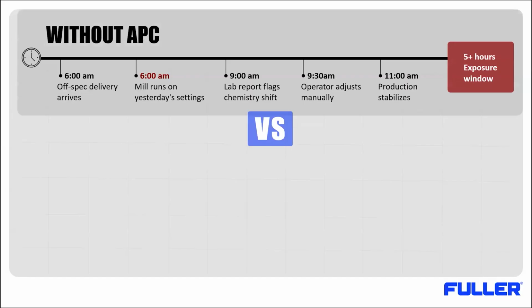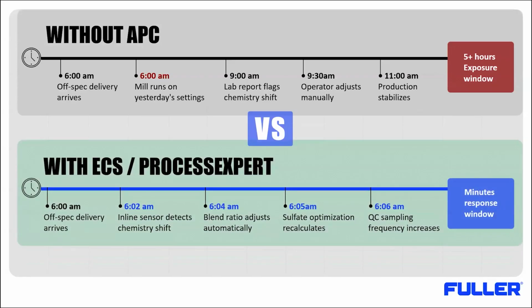The same Tuesday morning would look very different when the response loop is faster. Without advanced process control, the plant depends mainly on lab feedback and manual correction, a very long exposure window. With ECS or process expert and advanced process control, the target is to reduce that exposure window from hours to minutes. The system can detect the shift earlier and adjust the blend, change the operating target, recalculate quality-related settings, and increase the quality control response.